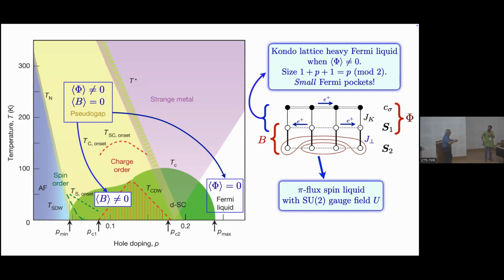Well, so it's over quite a wide range numerically. It has correlation lengths numerically of hundreds of lattice spacings. Now, the critical spin liquid is supposed to be here. Now, when I lower the temperature, it has to confine, unless you fine tune. But in fact, as far as we know, the critical spin liquid is not totally stable from the numerics. So it has to confine. Now, the insulator, I quickly reviewed, confines either to the Néel state or the valence bond solid. The part that I skipped is in the doped material, when B condenses, it confines into the D wave superconductor.